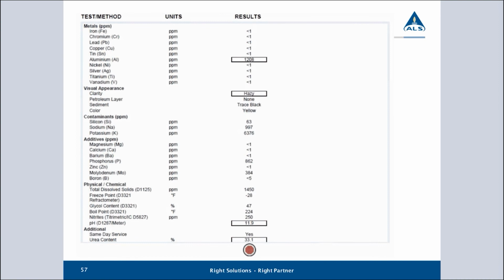So what has most likely happened here is this cooling system has been dosed with DEF, and that is strongly alkaline, and alkaline solutions will dissolve aluminium. So what we're seeing here is somebody has accidentally put DEF into a cooling system, and this has triggered a very strong corrosive attack on the aluminium components of the system. Literally, when pH is much above 10.5, once it reaches 11 and greater, your coolant is literally dissolving the aluminium, and this will happen extremely rapidly.